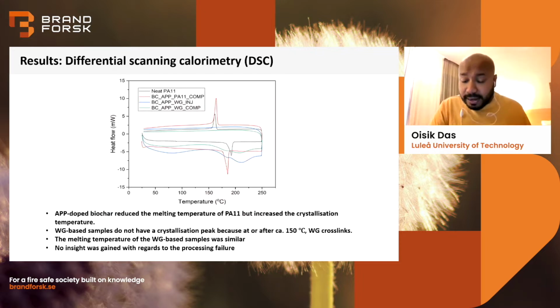However, to understand better why the compression molding of polyamide 11 and the injection molding of gluten were causing problems to form the samples, we have done further analysis. So first, we have done differential scanning calorimetry to understand the thermal properties of the composites. We can see that when we add the APP doped biochar in neat polyamide 11, the melting point has reduced a little bit, but we can clearly see it has increased the crystallization temperature. And this is because the biochar particles acted as nucleation sites from where crystals were formed.